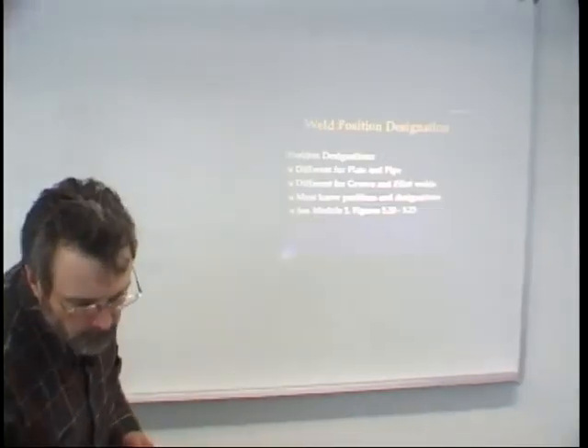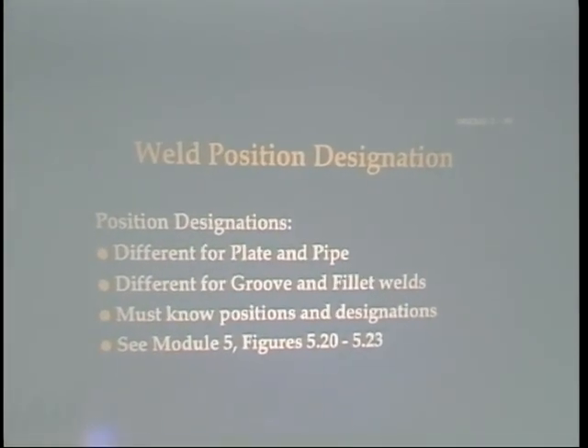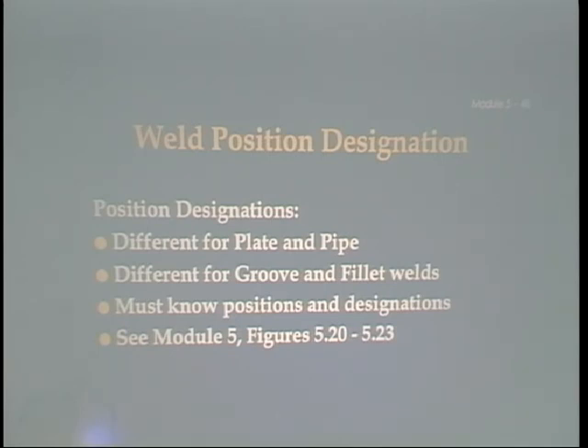We're on page 530 now. Highlight: 'If the welder qualifies on pipe, he or she is automatically qualified on plate.' Plate groove qualifications in the 3G and 4G positions qualify the welder for all positions of plate. Qualification in either 6G or 2G and 5G positions qualifies the welder for all positions of pipe, except T, K, and Y connections. The 6GR test position, however, provides full coverage for all pipe positions and configurations. These numeric designations should be remembered by the welding inspector.